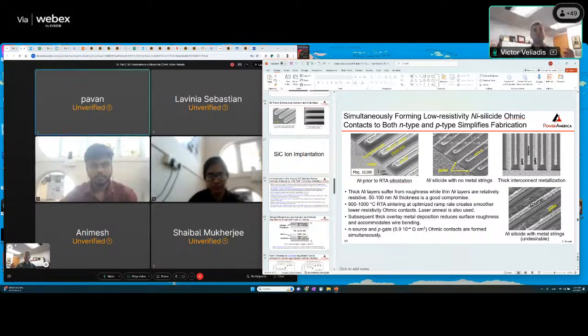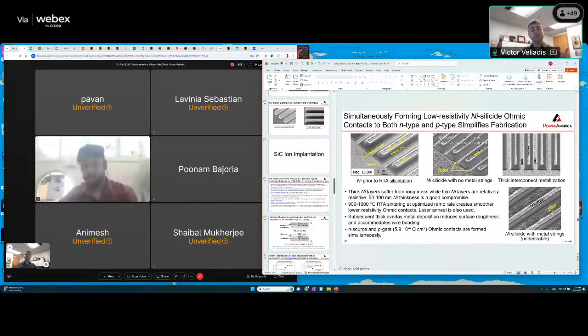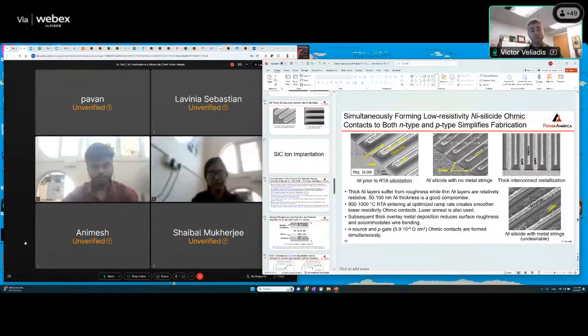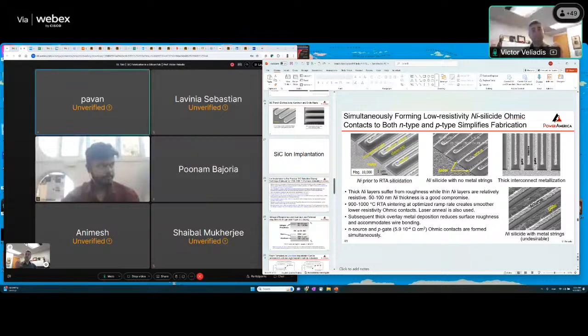Now, the second thing is the basal plane dislocations that I mentioned before. They will have a small impact on a 600 volt or a 1200 volt device, but basal plane dislocations, if they're present in the epitaxial layer for a 6.5 or 10 kV device, and I can send you publications that I have on that, will really degrade the device pretty badly. Okay. So the other thing is we need to have clean epitaxial layers that do not have basal plane dislocations. And remember, basal plane dislocations can come from the material, the epi layer that you have, they propagate from the substrate, but also basal plane dislocations can be generated during the implantation process, depending on how you do the implantation. So there is a lot of work and a lot of reward in making these high voltage devices. And the biggest aspect that you have to tackle is making a good quality, thick epitaxial layer.